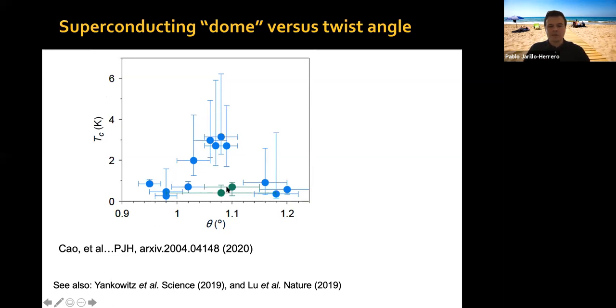These two dots here are particularly disordered devices, so don't pay too much attention to them. These are the devices for which there's less disorder, they seem to form a dome. And having recent experiments by Dima Efetov and by Andrea Young and by other people, and Corey Dean, you could probably add another half a dozen or dozen points, and they sort of seem to fall roughly here. The lowest angle for which we in my group have seen superconductivity is 0.95 degrees.